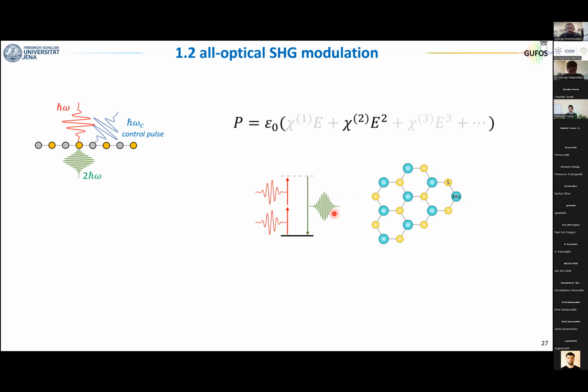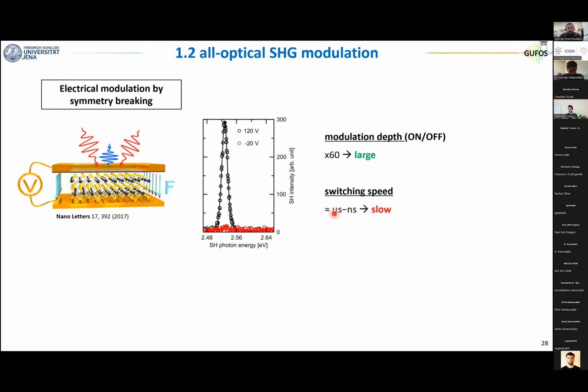Before I tell you what we did, maybe a brief state of the art. So when we started this project, there were already 2 main approaches to tune the nonlinearities in the transition metal dichalcogenides. The first one is the electrical modulation. Even here, there are different possibilities. The one that I like the most is the one that is based on breaking of space inversion symmetry. So now you can take a bilayer. Bilayer TMDs are centrosymmetric. You can now apply an out-of-plane electric field. And with this out-of-plane electric field, you break the symmetry. So now you see that as a function of gate voltage, you have a very large tunability of the nonlinearity. The advantage is that the on-off ratio is very large. So you see this goes, I mean, this is a factor of 60.